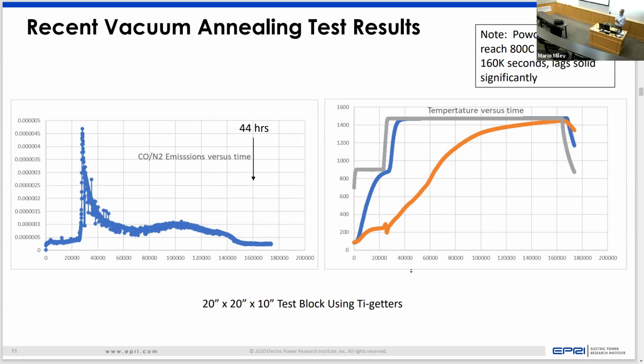You look at this, we went out to almost 28 hours before we actually arrived at the temperature where we thought we were after about 6 or 8 hours. So we were not fully getting to that annealing temperature to get rid of residual gases. Hence, they stayed, we still had oxygen in the part, and our toughness was much lower. We were able to show at different locations, elevations in one of those sections, that we weren't getting the right temperatures. So again, it affects microstructure, it affects oxygen content, it affects toughness. Hope I answered. That was a long answer for a short question.